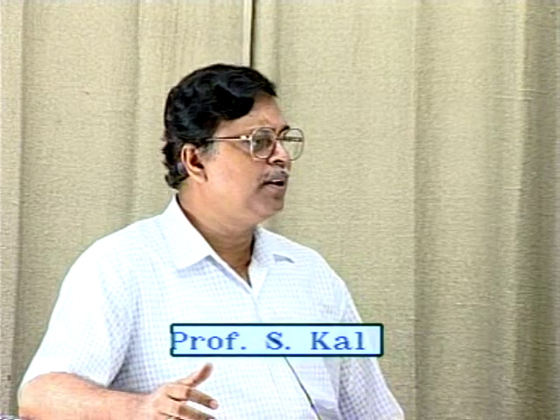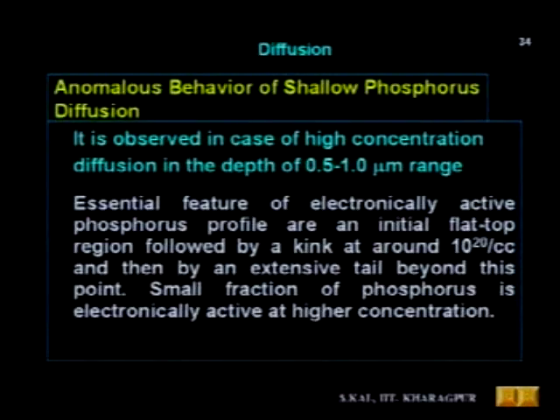So anomalous behavior of shallow phosphorus diffusion has been observed. That is, in case of phosphorus, if the doping concentration is extremely high, then the normal pre-deposition doping profile we never get. Rather, the doping profile is not similar to the error function diffusion, and some difference is observed. You will see at the surface a flat region, and then a kink region, then a broad tail.